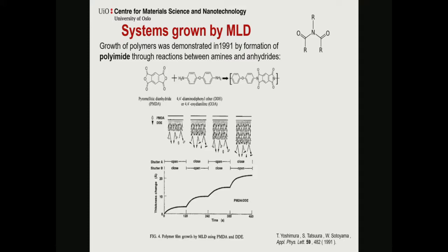You will notice that the saturation times are somewhat long. They are somewhat long for numerous reasons. One thing, polymeric reactions without catalyst, without solvent that maintains the protons, is not really in your favor from the beginning on. But also, here they use a fairly low temperature on the source, much lower than I would anticipate. And ergo, the flux of the precursor to the substrate is fairly low. So this is possible to speed up.